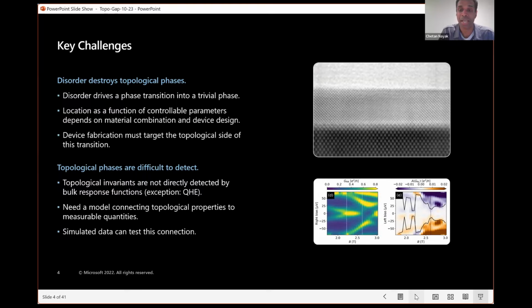So what we have here is a TEM image of a type of device that I'll explain in more detail shortly, that involves superconducting and semiconducting layers. And you can see here, because this is grown by molecular beam epitaxy, the atoms are more or less perfect crystals in perfect atomic registry between one layer and another. Any disorder on top of that is extremely harmful because it will ultimately drive a phase transition to the trivial phase. So however you manage to fabricate this thing, and of course it depends on the particular material combination and device design, your process must be capable of getting you to the topological side of this transition. Otherwise you end up on the trivial side.